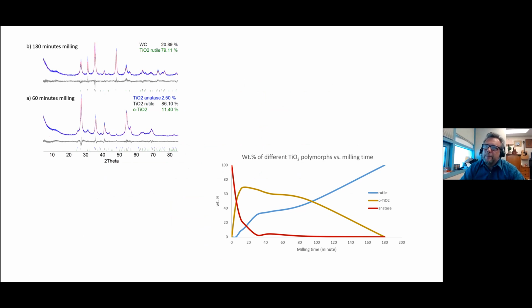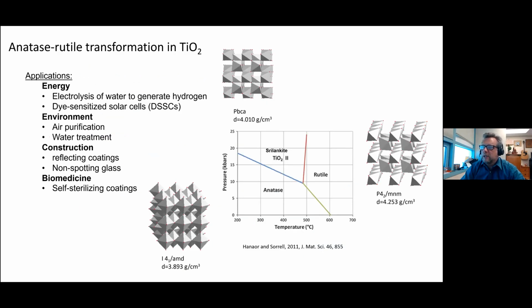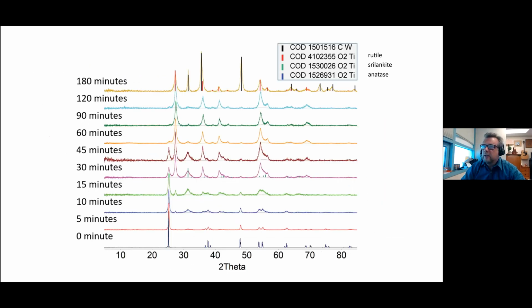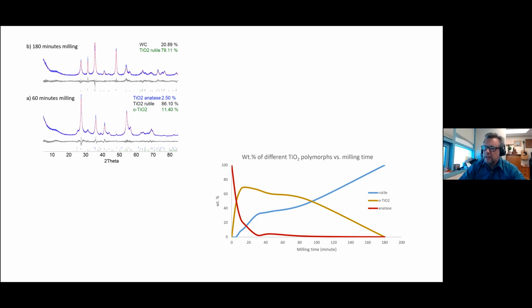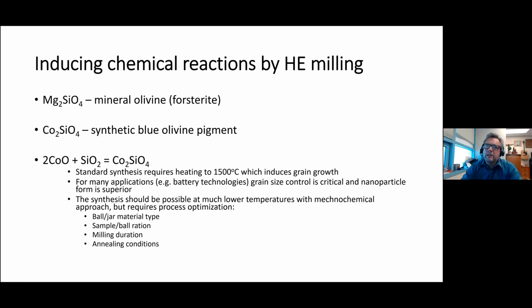So again, you can analyze your product pretty nicely. The powder statistics is very good and allows for high quality Rietveld refinement. You can monitor how the phase fractions for each phase develop as a function of time, which allows you some estimation of the kinetic parameters of this process. So encouraged by these first 2 experiments, we decided to play with chemical reactions.